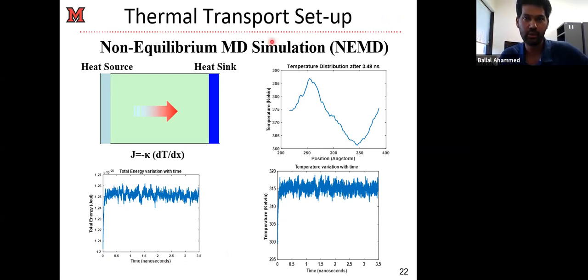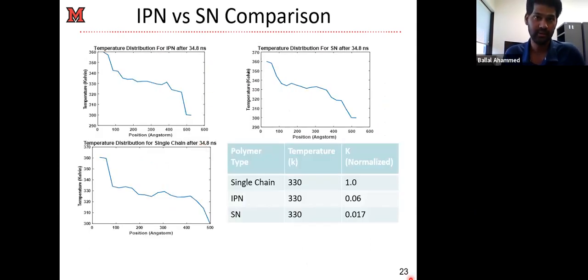So we use the non-equilibrium molecular dynamics simulation. As you are maybe familiar with this kind of stuff, we define heat sources and heat sinks. And when our system equilibrates, we get our temperature distribution, which is a straight line from the heat source to the heat sinks. Then when you plot this temperature distribution, you get the slope by fitting a line. And you also measure the heat flux from your MD calculations. After that, you can calculate your thermal conductivity from there. So that is the method. You may be familiar with it. So now let's move forward.